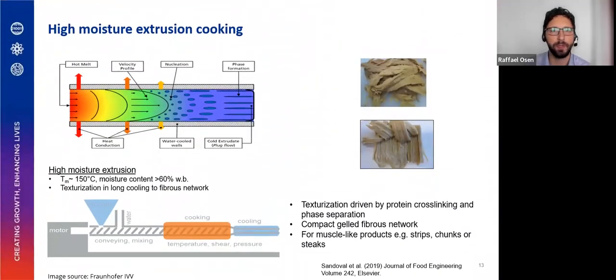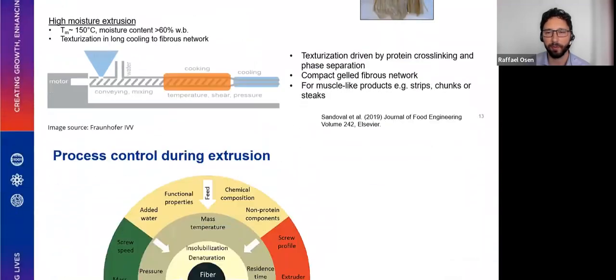Another version of this process is a high moisture extrusion process, which uses higher water contents, higher protein contents during the processing. And then instead of pushing this material through a small die, it is pushed through a long cooling die, which facilitates a laminar flow profile. It avoids the expansion of the material due to water evaporation, and then facilitates a texturization in a laminar flow profile, which is driven by protein cross-linking and phase separation phenomena. The products are shown here on the top right. It's more of a gelled fibrous network with a high water content, 60 to 80%, and this can be used, for example, for muscle-like products such as strips, chunks, or steaks.